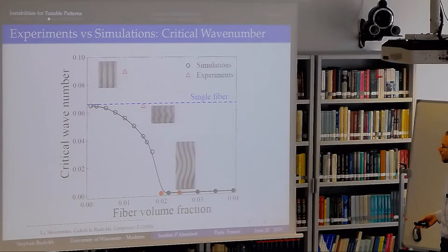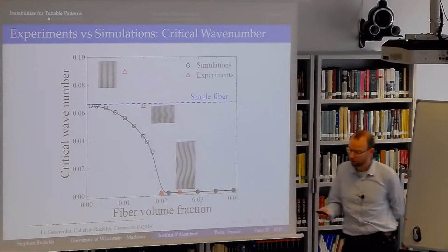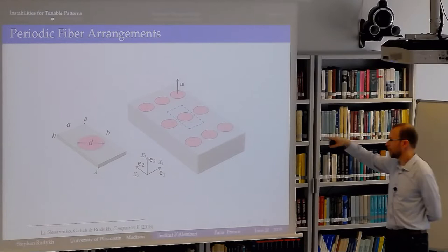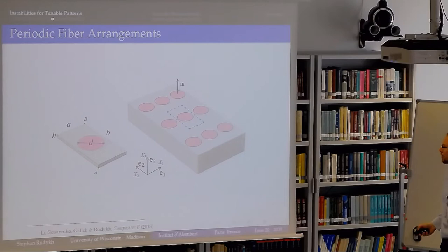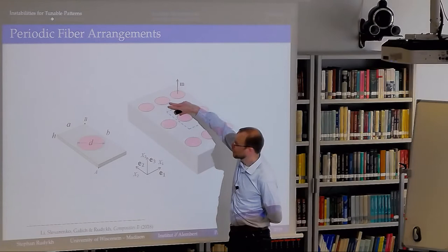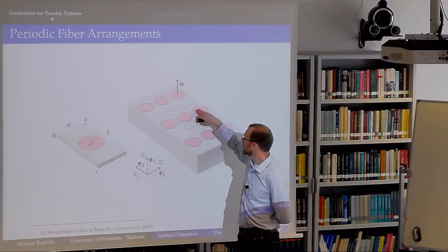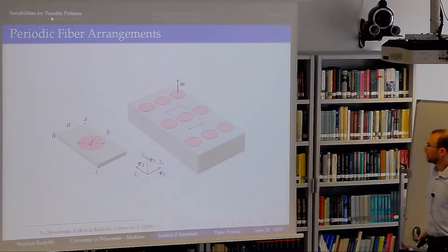So what we also looked into, trying to understand maybe why or when, what affects the helical patterns and maybe we can obtain them, is that we can also control the instability by positioning these fibers in a certain periodic manner. So putting them close in one direction, farther in another. One of the things I saw is that once we give more space in this direction, so it becomes softer, the fibers should buckle in this direction, which appeared to be not the case. Actually, it works in the opposite way, which wasn't apparent to me entirely.